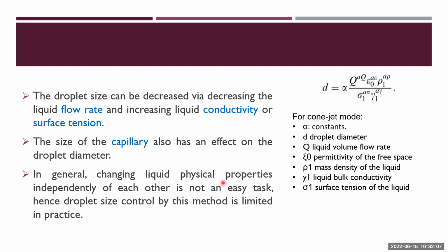In general, changing liquid physical properties independently is not an easy task. This is why we don't change the formulation. If you want to change the conductivity, you need to add one material. This material will affect the surface tension and may affect the viscosity. So it's very difficult to change the physical properties independently. Basically, they will change altogether. So I'm always trying to avoid playing with the formulation. After we fix the formulation, we play with the process.